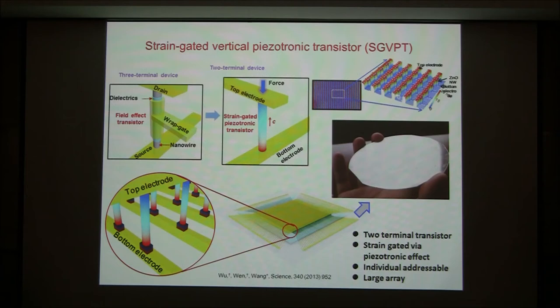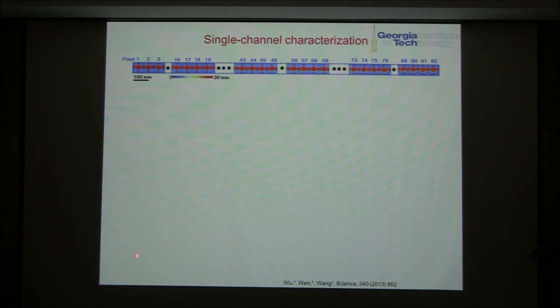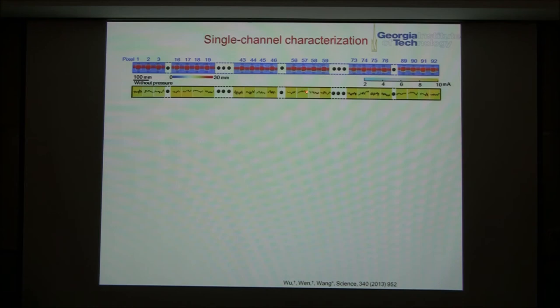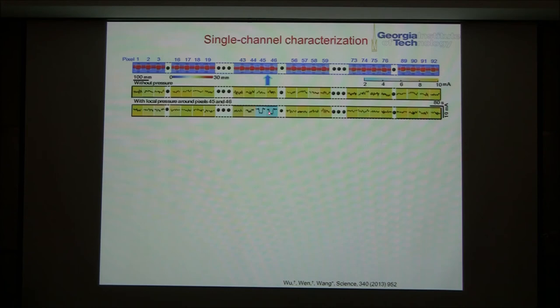Now, let's look at how this works. Let's analyze 92 of these channels — 92 of these transistors across this way and 92 this way. We can measure the transport on a fixed bias, and you can see the current response. If you apply local strain here, you can produce a lot of tuning. This changed current gives you the signal. But this can be two effects — it could be piezo-resistive effect, and it could also be piezotronic effect. Which is which?